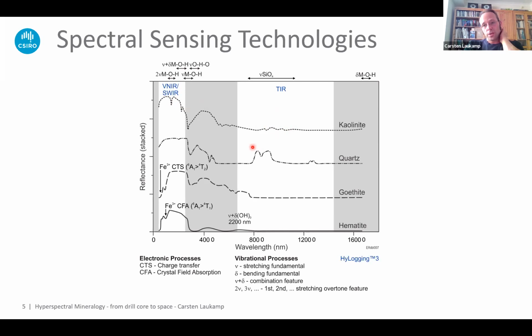If you're interested in quartz, then you need the thermal infrared mainly, because quartz doesn't contain any hydroxyls, at least nominally it doesn't contain any hydroxyls. Therefore, you will not see any absorptions in the short-wave infrared. So if you're working in the skarn system, for example, where you don't have that many short-wave infrared active minerals, you need thermal infrared basically.